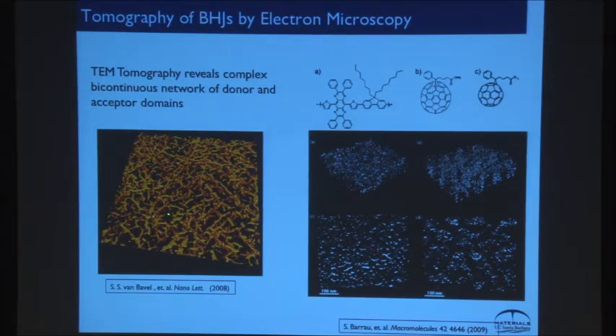And so the scale bar here, these are maybe 20, 30 nanometers, but there's some cutoff that people use in TEM tomography. So you don't know how abrupt these interfaces are. So you have to be quite careful. But just to give you a sense of this, these are very complicated networks that the charge is coming out of. It's not like there's this perfect straight line path between the bottom and the top. The charges have to fight their way through this very complicated looking network.